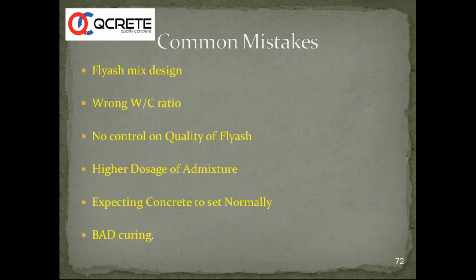And most importantly, last but not least, any SCM, especially the concrete with fly ash, needs good curing. Good curing, both in the initial stages. You need to control the rate of evaporation of water from the surface, and you need to protect the concrete either by plastic sheets or by making the bunds quickly the next morning itself,